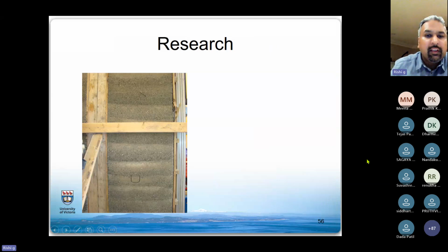Very, very interesting. This is an 8-foot wall, I think, if I remember correctly, a full-scale wall that was constructed. You can see the beautiful layers here. Some of you may be wondering how these layers are formed. What ends up happening in rammed earth is you construct your forms. You put down about 6 to 8 inches of material in the forms, which of course you cannot see. Then you compact it down to roughly 3 to 4 inches of layer. Then you go with the next layer, put about 6 to 8 inches of fresh material and compact it down. So you never know what's happening in the form. But fortunately, when you strip it, the natural texture just looks amazing.